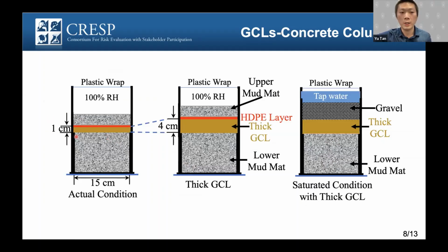And also, as we were concerned that the GCL is pretty thin, only 1 centimeter, we would like to learn more about what happens in the cross section of the GCL. So we created a 4 centimeter thicker GCL in our lab. We call this the thicker GCL scenario. The other conditions are the same as the actual condition that we set.